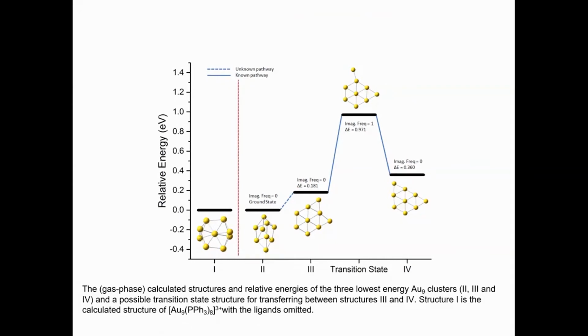The record before us was gold 39, which is a gold cluster with 39 atoms, and visualizing a very small gold cluster, just 9 gold atoms, is very hard and very challenging, because you already deposit some energy from the electron beam itself, and this is an energized cluster, and it's very hard to identify this gold nanocluster.